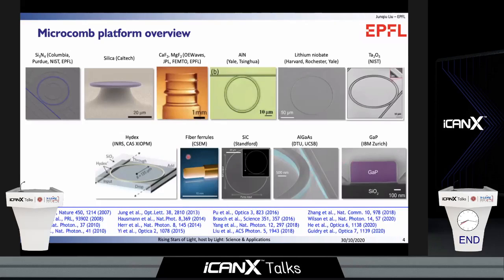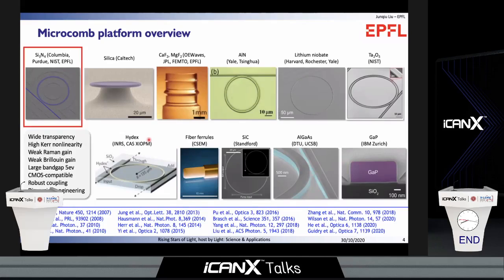Now, so far, microcomb has been demonstrated in a wide variety of material platforms. For our research, we built photonic integrated circuits using silicon nitride. The advantages of silicon nitride include a wide transparency window from visible to mid-infrared, high Kerr nonlinearity, but simultaneously weak Raman and Brillouin gain. It has a large band gap of 5 electron volts, which makes this material immune to two-photon absorption in the telecommunication band. Also, the fabrication process is CMOS compatible, and you can have a robust bus waveguide to ring resonator coupling. And you can also apply dispersion engineering, so that you can alter the waveguide geometry to tailor the group velocity dispersion.